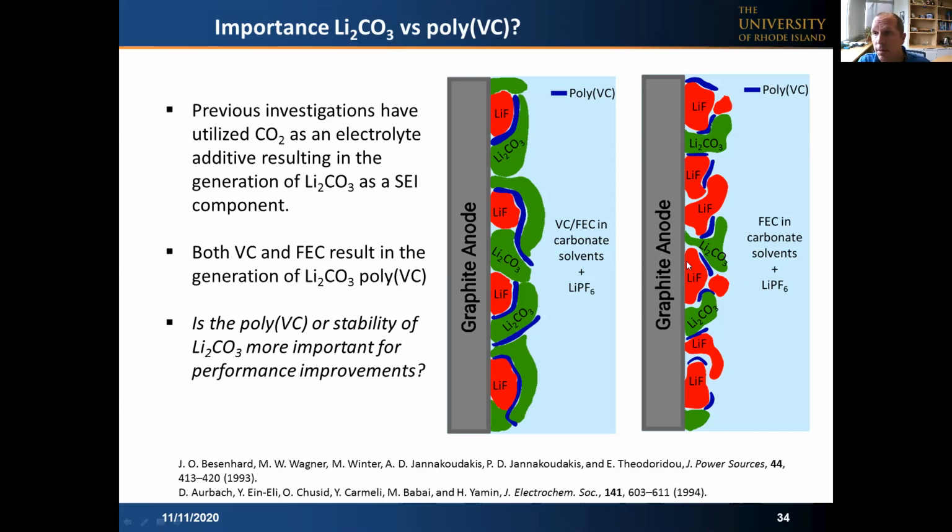Because we know that lithium carbonate is significantly more stable than the lithium alkyl carbonates, and previous investigations by Martin Winter and Doron Aurbach had utilized CO2 as an electrolyte additive, where they pumped up cells with CO2 gas, and they observed a significant extension of the calendar life of the lithium-ion batteries and a more stable SEI.